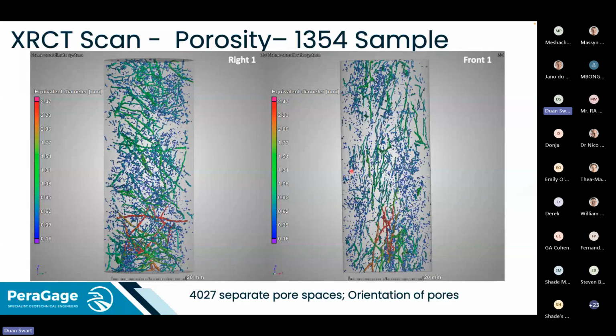So this is the sample that you saw in the video, just from the right, the front. You can see that we didn't get very small pores. It's only 0.16 on this sample. But what I want to show you is that the pores do have a preferred orientation, which is parallel to the structure that we saw in the logs and also on the density scans. In this sample, just for interest's sake, we picked up 4,027 separate pore spaces, and there will be a lot more in a lot smaller pores.